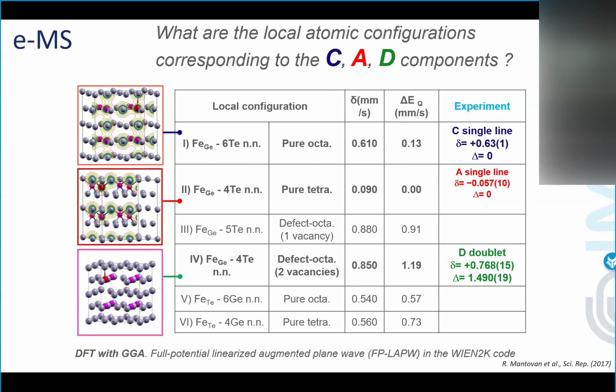In the crystalline phase, the C component was still iron sitting there, in the octahedral configuration of 6 surrounding tellurium atoms. And the broad doublet is mostly due to implantation-induced damage, which is a con of the method. You are implanting very few atoms, but you are implanting, so you have some sort of damage. It was this additional doublet.